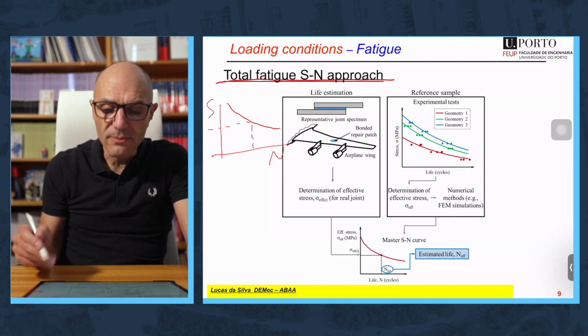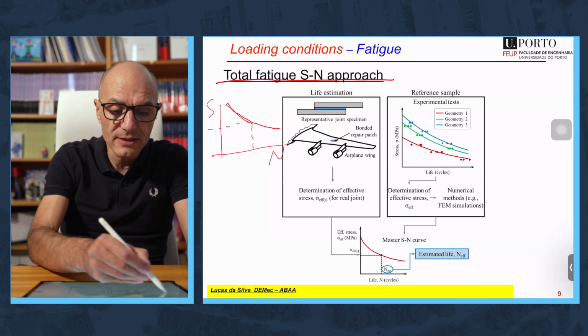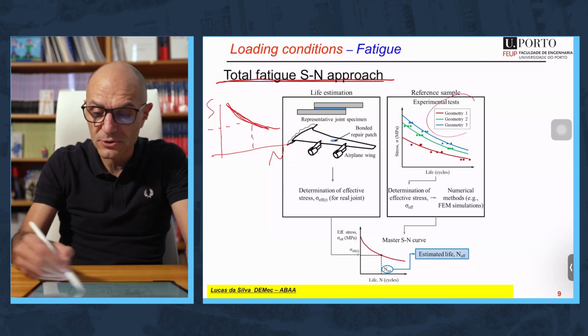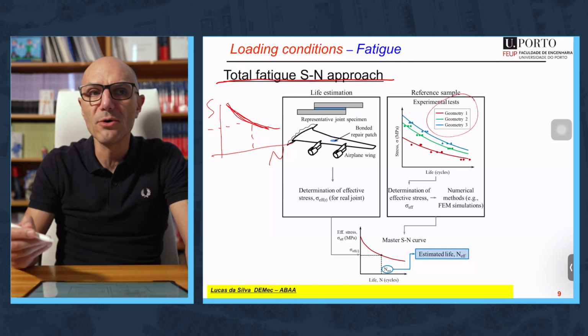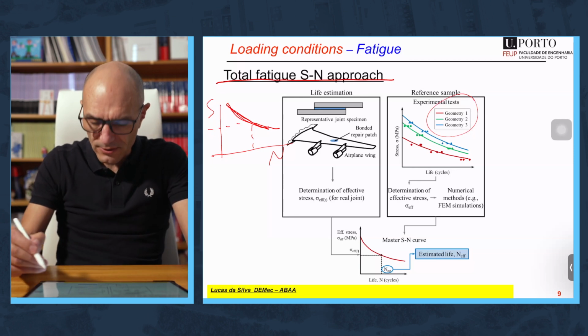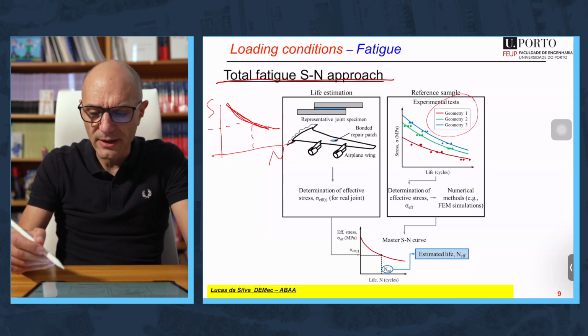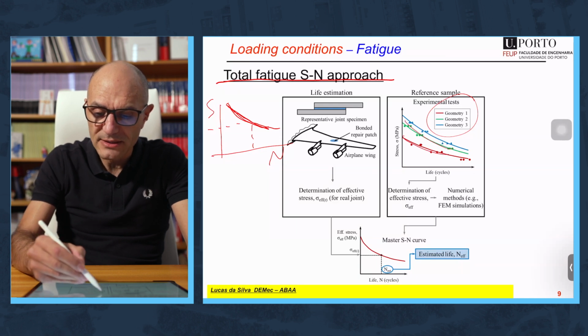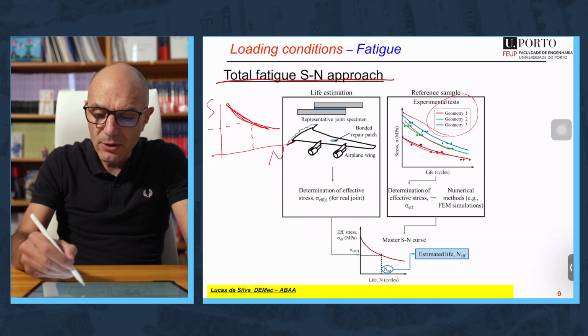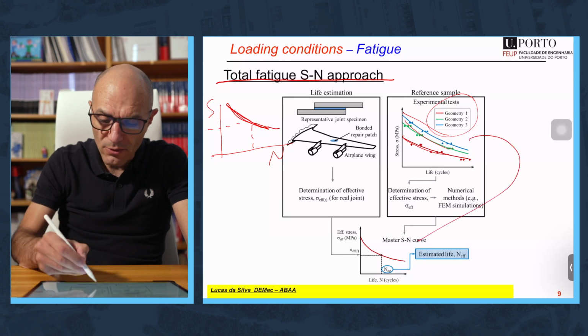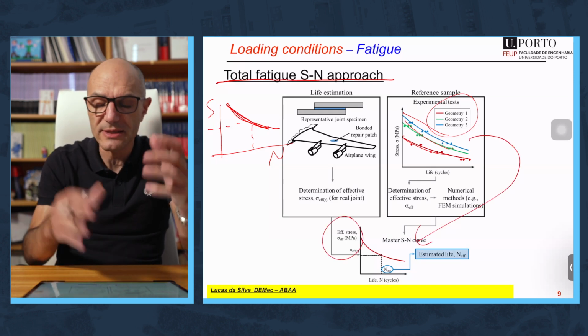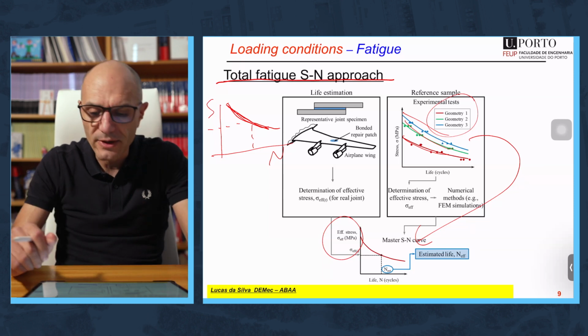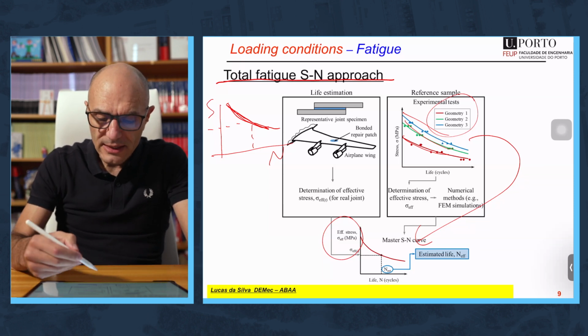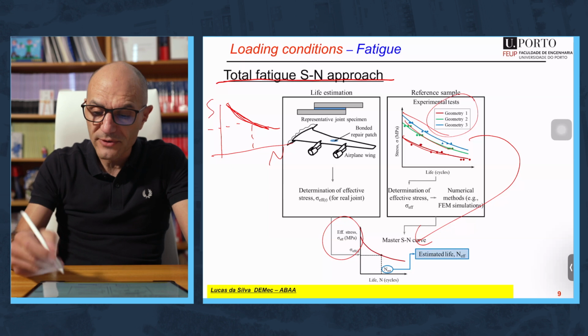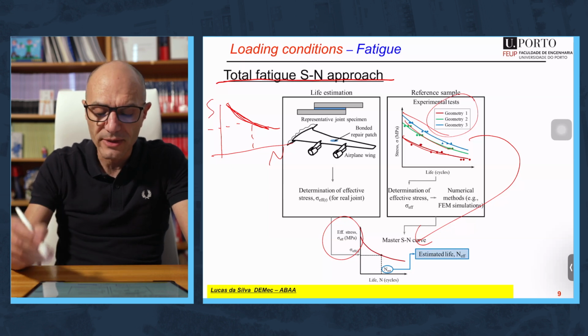In this slide you have something a bit more complicated, because in fact this SN curve can vary a lot as a function of the geometry and the loading mode, if it's mode 1, if it's more mode 2. So we have recently been looking at this, and we have generated different types of SN curves as a function of geometry, and we collapsed these SN curves into one using an effective stress, a stress component that takes into account several types of stress. And this allows us to have only one curve that takes into account these factors, the geometry and the mode mixity.